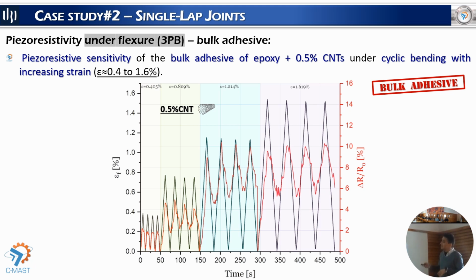But here the electrical signal is not as clean as it was in the first study. In any case, I would say that this signal is the signal measured directly by the multimeter. This signal was not filtered, was not optimized, so we know that we have space for some improvements here. But the most important conclusion of this test is that this adhesive, composed of epoxy resin added with carbon nanotubes, is really sensitive to electrical resistance variations when mechanical stress is applied.